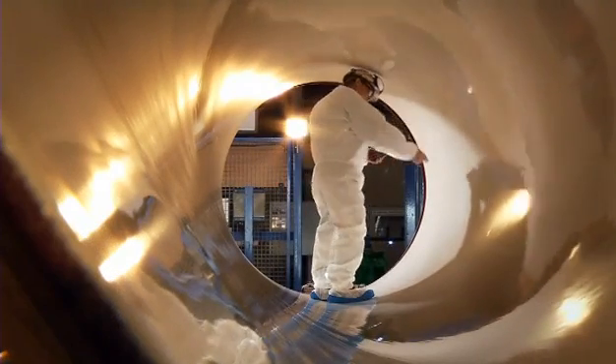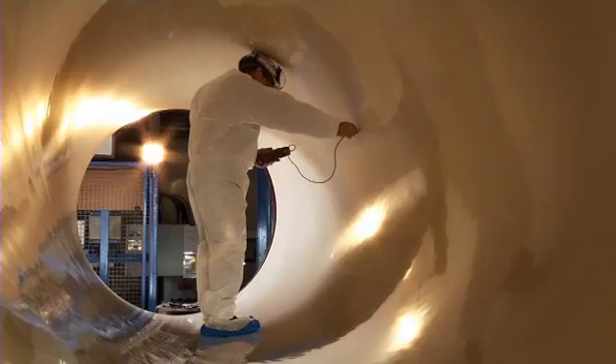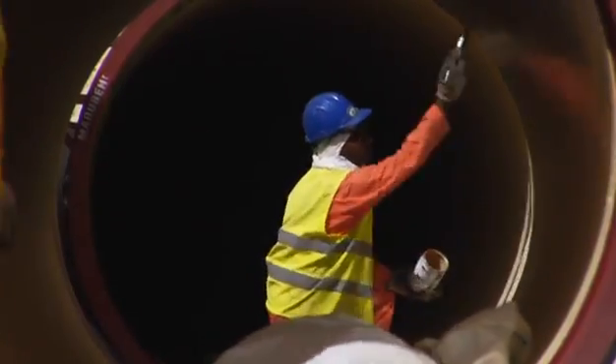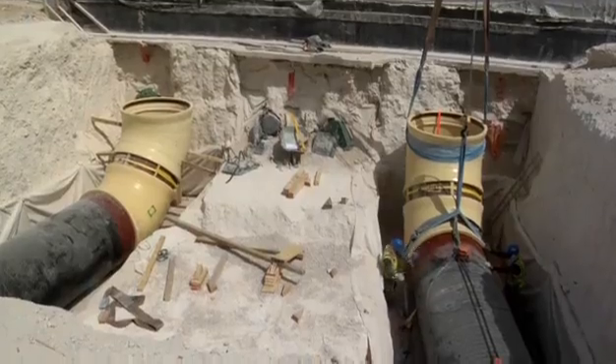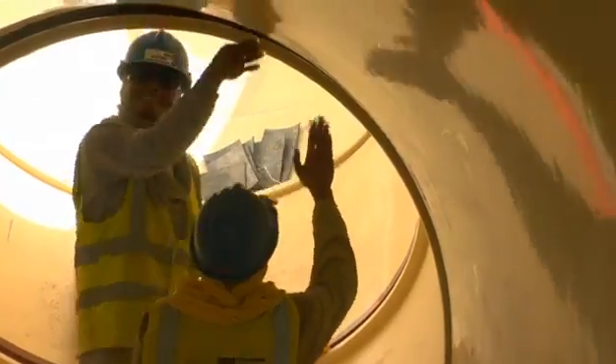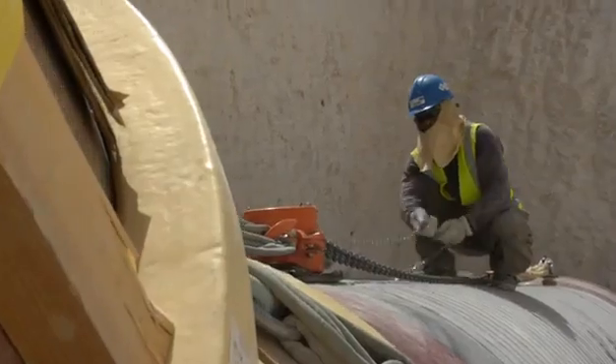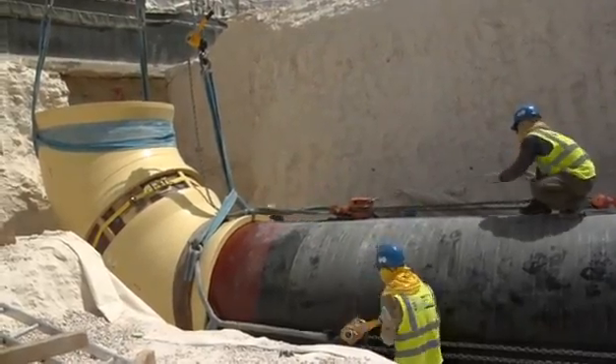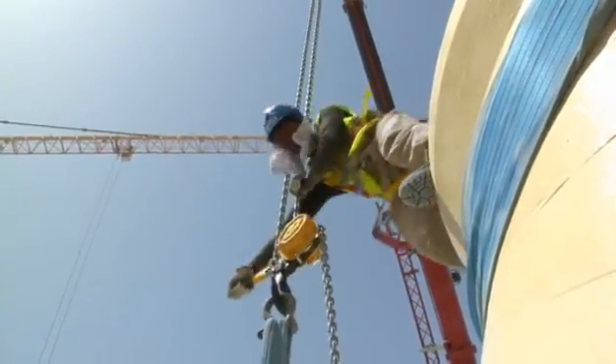The inside of the pipe is coated with a 1,000-micron layer of polyurethane, which permits a perfect flow of effluent. This is a pressurized pipe with back pressure — pressure involves pumping, and pumping involves energy. Having a smooth coating with reduced internal roughness permits a perfect flow and allows us to use less heavy pumps, thereby consuming less energy in the long term. The client has focused on reducing long-term energy and operational costs over the next 40–50 years, and this polyurethane coating provided by Saint-Gobain PAM permits the client to reduce their energy consumption substantially.